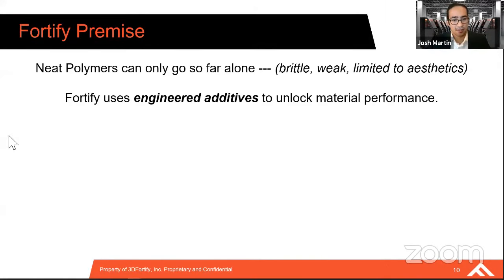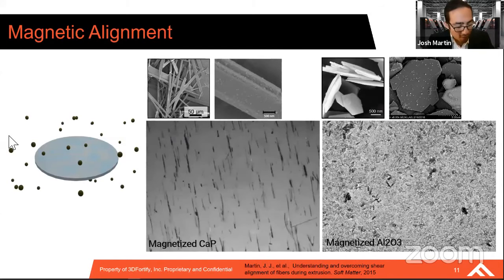It turns out that in a melt thermoplastic, you have a tremendous amount of high viscosity material, which means you have a lot of shear forces, a lot of shear torque that you have to overcome. And long answer, I don't believe that's a very viable path, because in extrusion-based FDM you'll see a lot of shear-dominated alignment. There have been a few groups that have done tremendous work. Jennifer Lewis's lab has done a lot of work characterizing how shear flow affects fibers while they're extruding from a nozzle. And so that was an area that we first explored and found that within a photopolymer, due to the relatively low viscosity of the resins, we can get much more effective alignment.